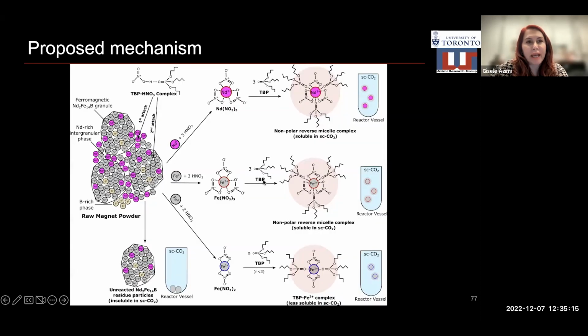Here we propose a mechanism for the extraction process. We say that the nitric acid attacks the metals, for example, neodymium, and it forms neodymium nitrate, so Nd(NO3)3. And this neodymium nitrate bonds with 3 TBP, forming this reverse micelle that has 3 nitrate and 3 TBP, and TBP has 3 aliphatic chains. So we have a reverse micelle with 9 aliphatic chains pointing outward, and this is a nonpolar compound that is soluble in supercritical CO2.